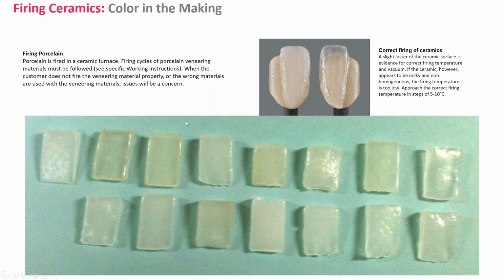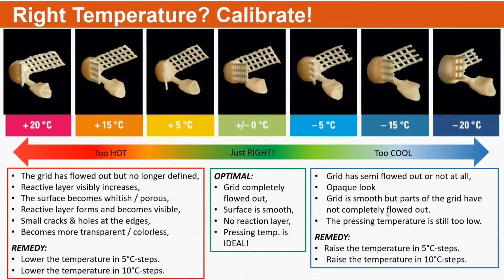Otherwise, if you're trying to achieve shade and your furnace is contaminated, even with a pressed material, you're not going to get the right shade, because all of those pigments, all of that contaminated material inside your muffle, floats into that ceramic as it starts to swell up and heat up and wet, right? So it's possible you can even contaminate a press inside of a ring as well. So make sure you do your tune-up occasionally for your restoration.